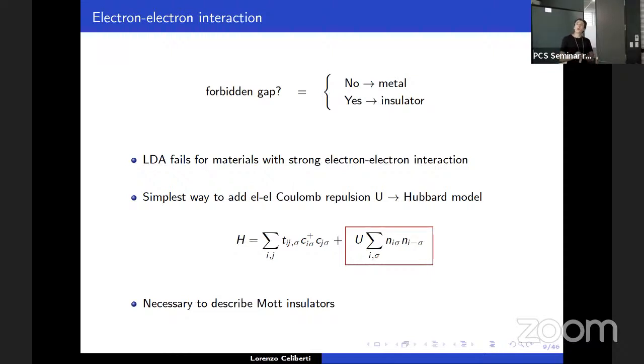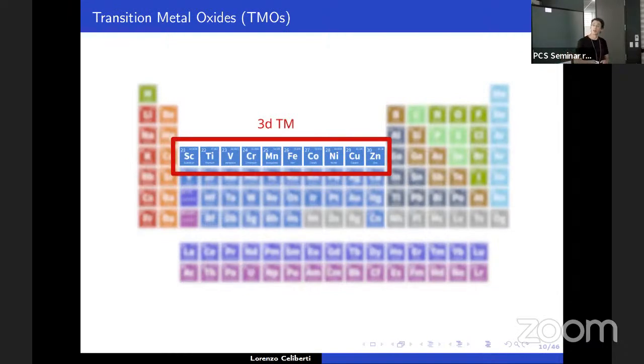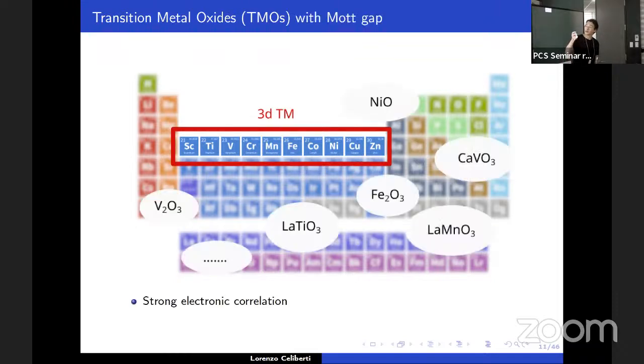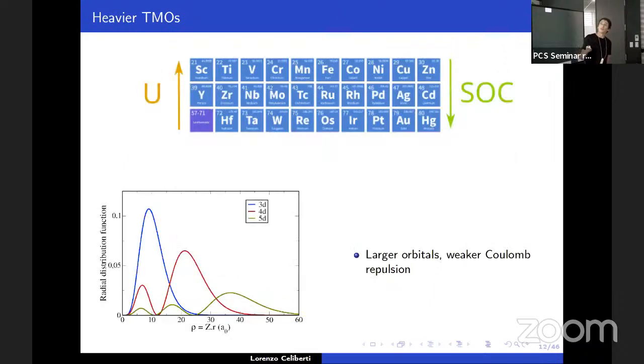And where can we find these materials? At least the first ones that have been found were transition metal oxides, in particular 3D transition metal oxides, so materials containing first-row transition metals. Among them, we have materials such as nickel oxide, titanates, manganates, and so on. If we look at transition metals, we have these general trends of the electronic correlation, represented by the Hubbard parameter U, which is stronger for the first-row transition metals and weaker as we go down.